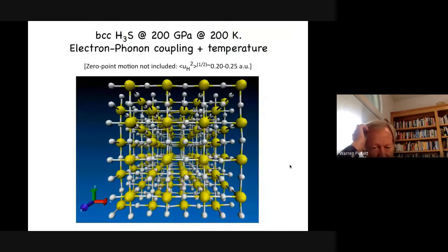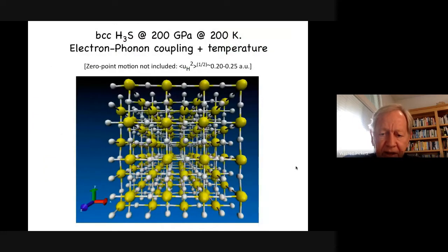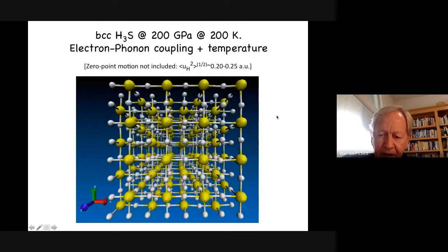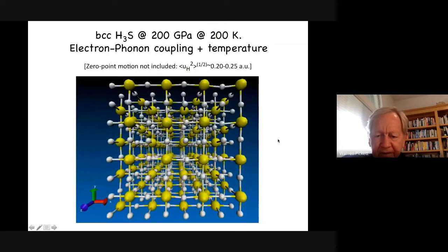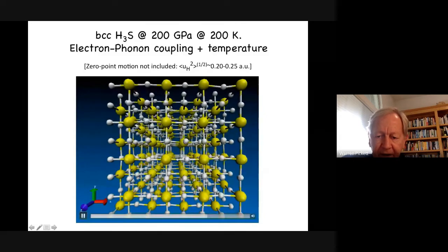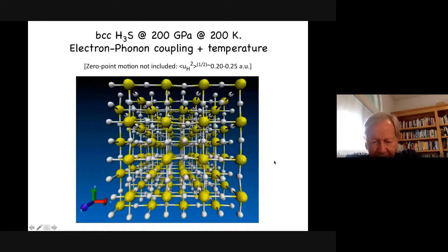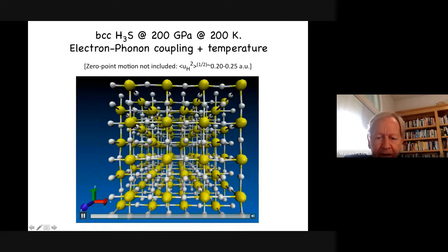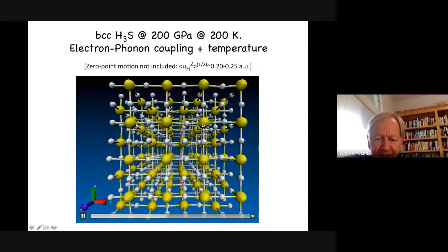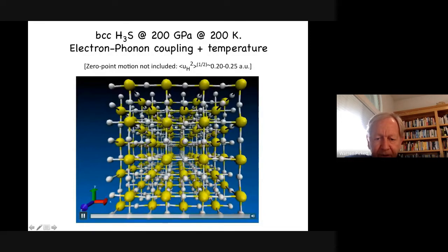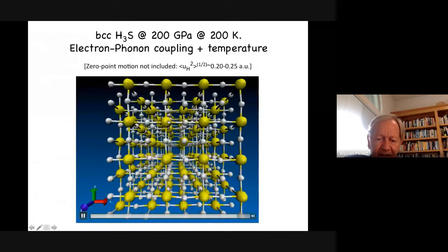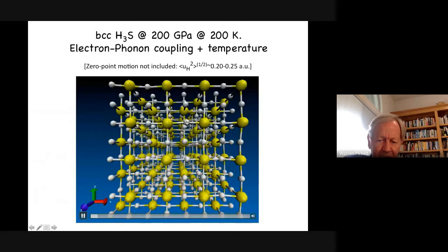So this is a simulation that my postdoc at the time, Antia Botana, and the world's expert on this kind of calculation, Francois Gygi, and I did. This is called an ab initio molecular dynamics calculation. Molecular dynamics with just analytic force fields or potentials have been done for decades, but only since really the 1990s have these forces been determined by density functional theory.